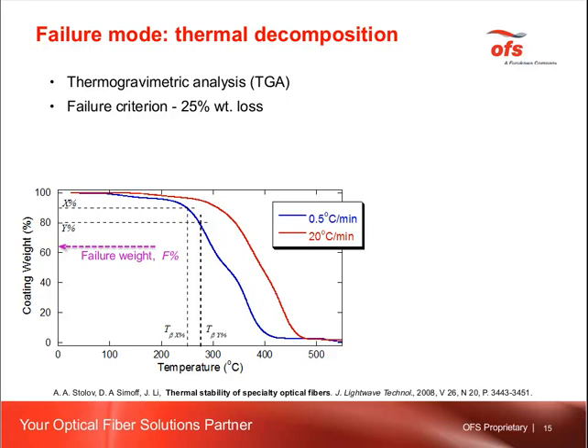Since the actual failure of the optical fiber depends on the application, and since we do not know in the beginning what the application of this fiber will be, we are free to select an arbitrary number. So we decided, let's take 25% weight loss as the failure criterion. So we assume if at an elevated temperature the coating loses 25% of its initial weight, that is the end of the lifetime for this coating and for this fiber.